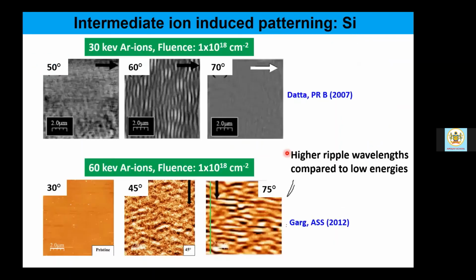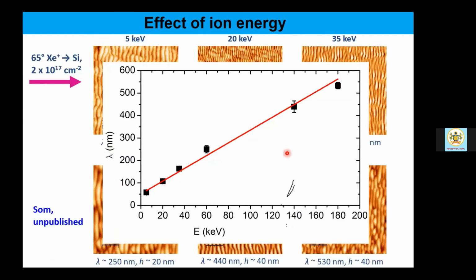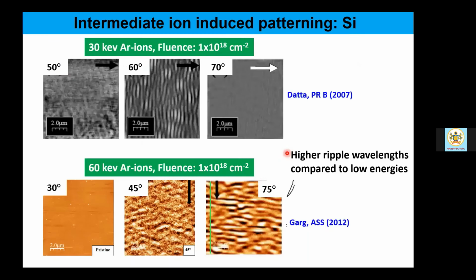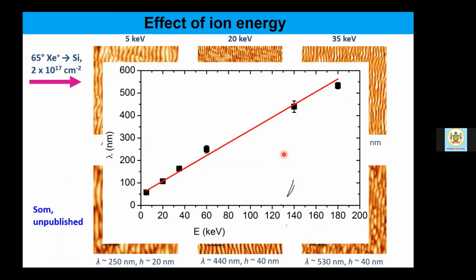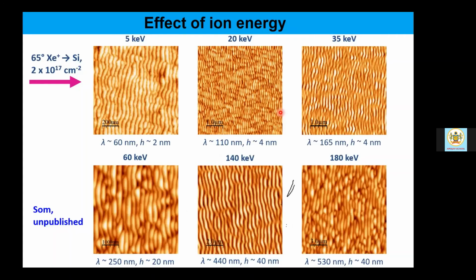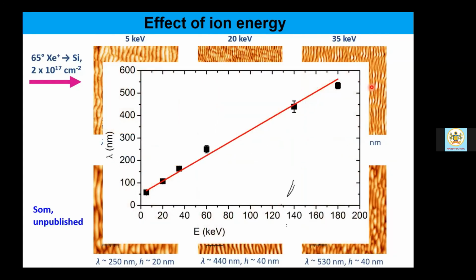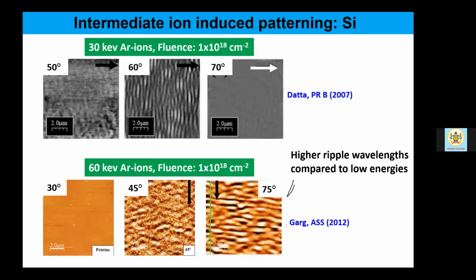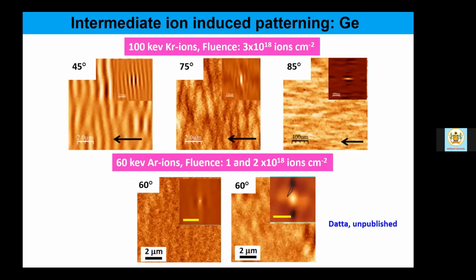So what happens actually for the argon ion induced pattern formation for silicon at a relatively higher, 5 times higher ion fluence, and we get to see similar formation of ripples as we saw here as well, at a comparable energy range, 60 keV and 35 keV, 30 keV, and like that. So higher ripple wavelengths are easily observed compared to that seen for lower incident ion energies.